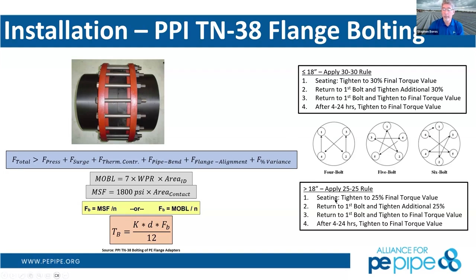If you're going to do greater than 18-inch pipe, you do the exact same thing, except you go through one more step and you only start with 25% of the torque value, an additional 25, and then the final value after, again, that 4 to 24 hour period to allow it to relax and creep a little bit, if you will, and make sure that you're going to have that final force where you have a flange that won't leak.